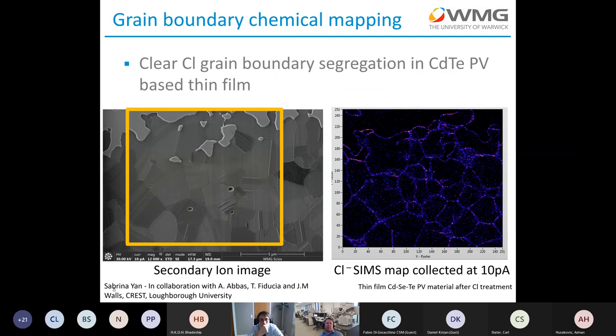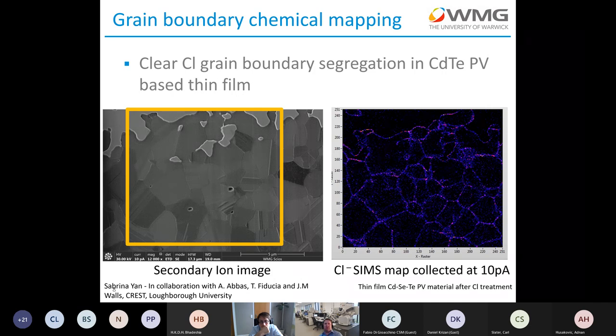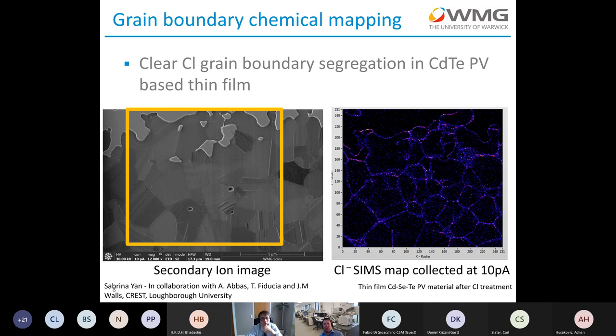The SIMS example I'll show is the only one not from a steel — it's from a thin-film photovoltaic with a CdTe layer. The SIMS clearly shows chlorine present at the grain boundary, something you'd normally only see in a TEM. However, SIMS sensitivity is very dependent on how easily the species is ionized, making it well suited to elements like lithium, sodium, and sulfur — very good for battery materials — but applications for analyzing steel materials are very niche.